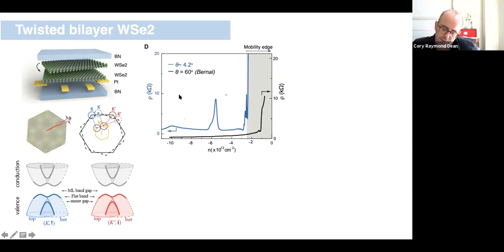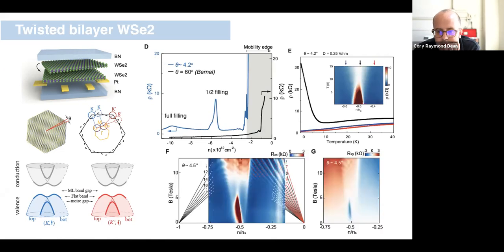Now, one of the challenges of these materials is that it's difficult to make good contacts to them. So it can be somewhat of a challenge generally to understand what your density values are. It's hard to pinpoint where the actual band edge is. Hall effect measurements are problematic because we're trying to measure Hall responses with very poor contacts in general. But as I said, we made progress, and in these devices we were able to address those issues. So we could identify not only that we have these peaks, but what filling they correspond to in the picture where we've created a low energy band in our system. Okay, so the way we do that is, sorry, I jumped the gun a little bit here.